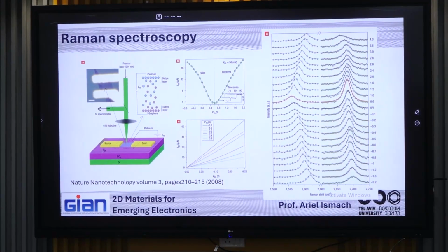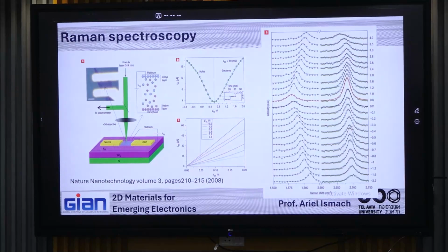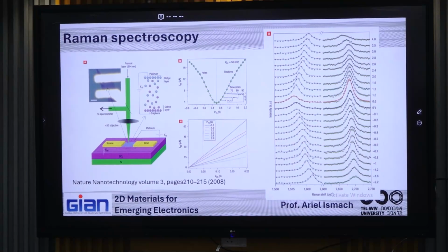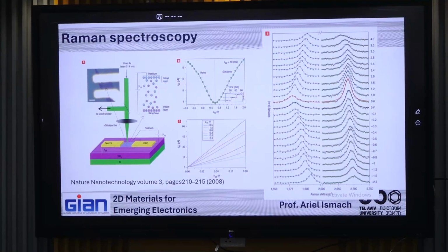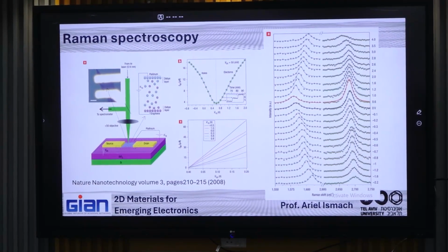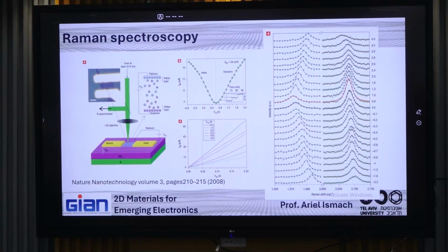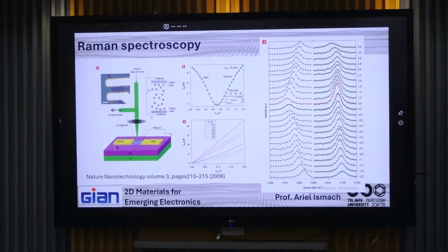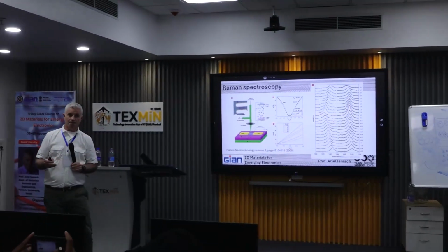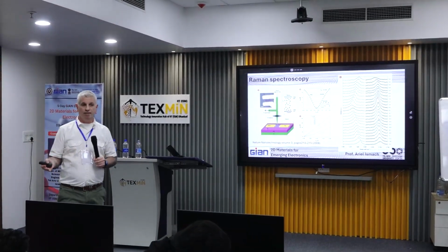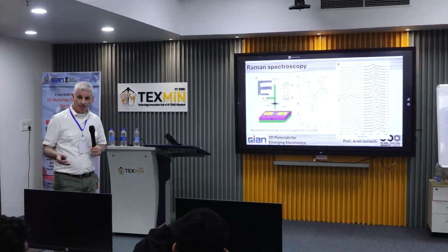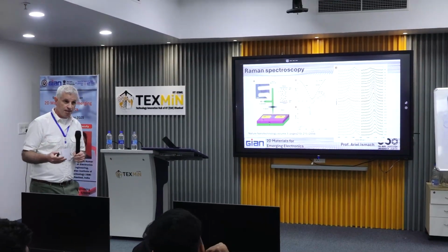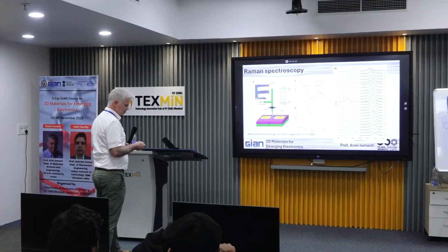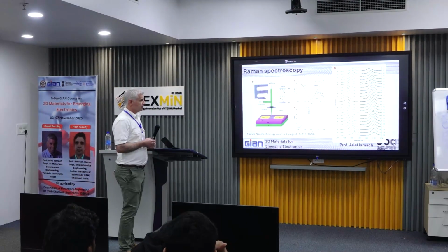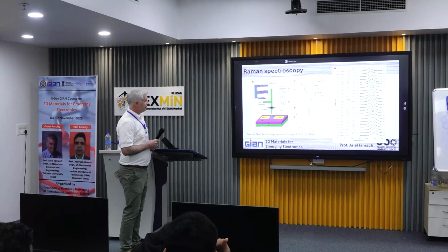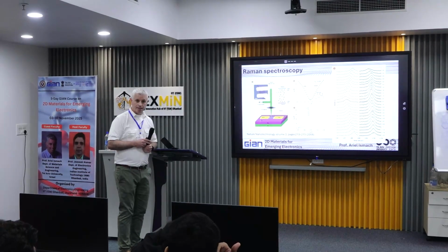Another thing that was proved very nicely with the Raman is regarding the G mode. The G mode is the mode of the vibration in plane of the hexagon. And the G mode is not sensitive to the number of layers, but is sensitive to a lot of other things. It's sensitive to strain, it is sensitive to charges, and therefore, for example, here you can see that the Raman was used to monitor